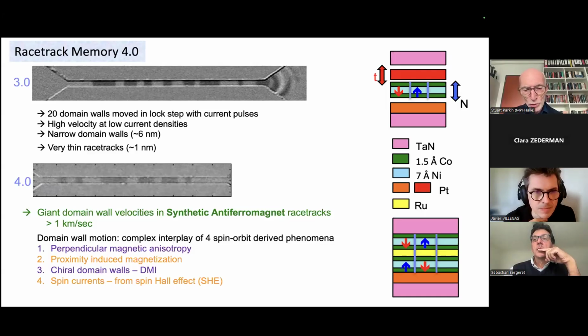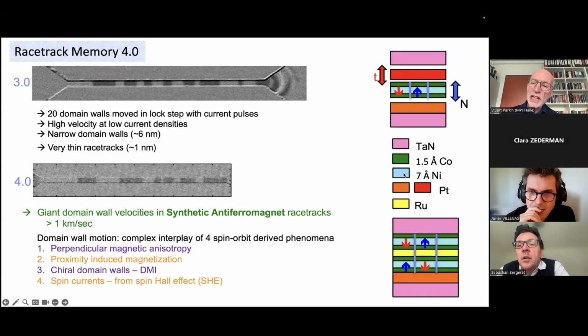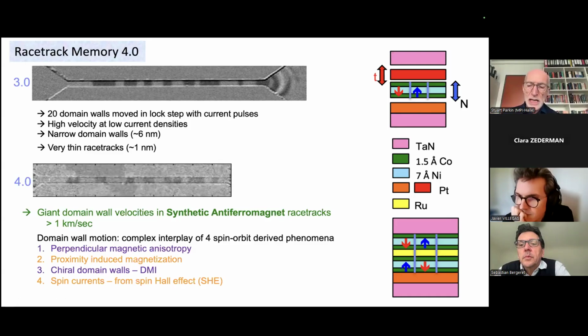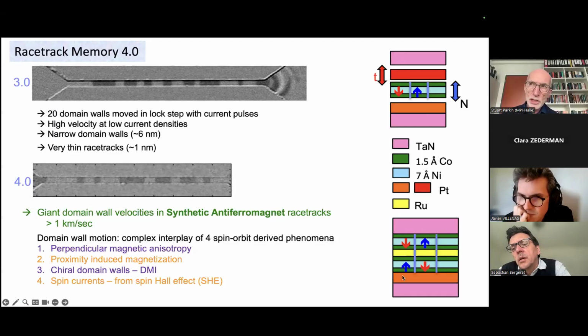I mentioned earlier, it's all due to interfaces. On the right-hand side, you can see a cartoon. The green and blue layers are layers of cobalt and nickel. They're just a few angstroms thick. So the actual racetrack magnetic layer is 1 nanometer thick. Underneath is a platinum layer in this particular case, which is a few nanometers thick. And down below in the synthetic antiferromagnetic racetrack, we build the two cobalt-nickel-cobalt sandwiches, sandwiched between them by ruthenium.